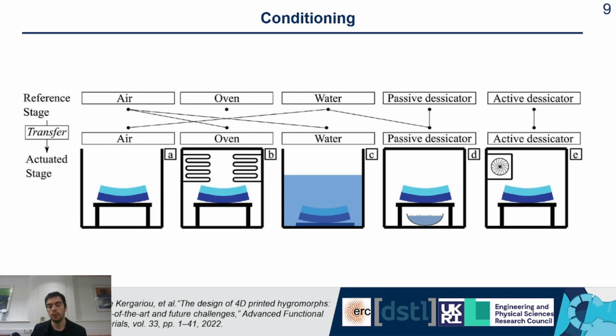To get more different actuation, researchers use desiccators, especially passive desiccators. They're boxes with salt inside, and this salt controls the humidity inside the box. And therefore, you are able to have different humidity for your specimen to control actuation at different levels of humidity. If you want more control of the humidity and temperature, then researchers use active desiccators, in which you don't need to open the box to change the humidity. You can just control it from the outside. Therefore, you have very good control of the actuation.